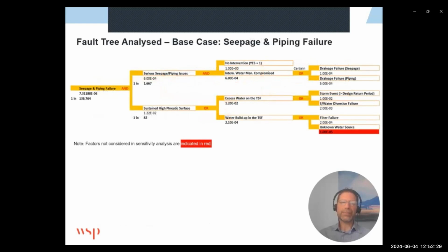Then if we look at seepage and piping failure, there can be serious seepage or piping issues and a sustained high phreatic surface in the facility. Those are the contributing factors that can lead to this failure mode. Factors not considered in the sensitivity analysis are indicated in red, and those are things that are hard to quantify, including, for example, the possibility of an unknown water source that contributes to water buildup in the facility, i.e. a fountain underneath the tailings storage facility.